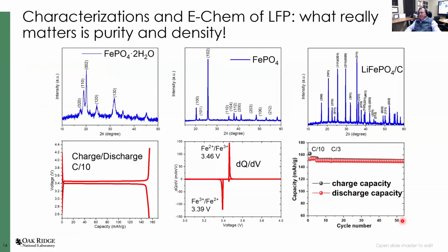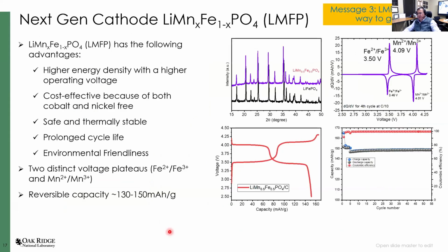This is some of the characterization. You can see the X-rays of the FePO4 before and after thermal degradation, removal of the water from the material, and the LiFePO4 on the right top picture there. You can see it's pure, but one of the key measures is really the capacity of the material. You can see we can get about 150 milliamp hours per gram. You can see the dQ/dV, and the cycling stability is very good. So more or less, this is congruent with what others have found, but probably the key finding here is truly a better performance and better packing density compared to others.